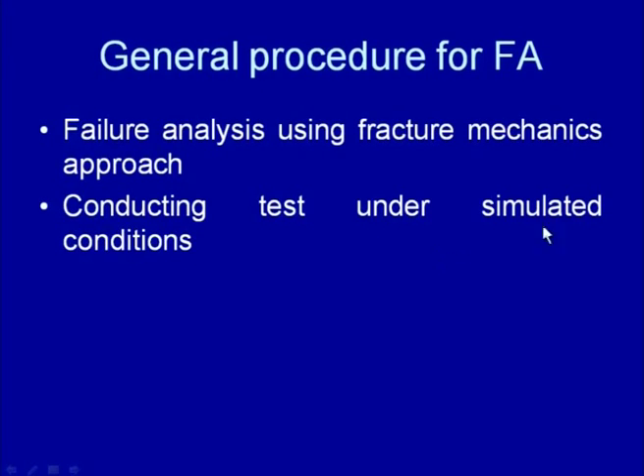Then sometimes we conduct tests under simulated conditions also, like if the component has failed in very low temperature conditions or very high temperature conditions, then in order to assess the performance of the material under those conditions, sometimes simulated tests are conducted. These are very specialized tests which will be performed under the conditions in which the material has failed. And the simulated conditions are developed, say if cavitation is taking place under very low temperature conditions during the service, then the cavitation test is conducted under those service conditions. Similarly, if solid particle erosion is taking place at high temperature, then we need to conduct the solid particle erosion test under those conditions. So, this will help us in establishing the behavior of the material under the service conditions to which it can be exposed during the service.